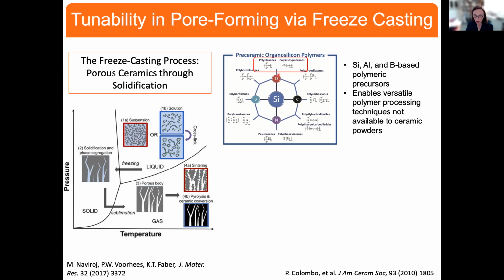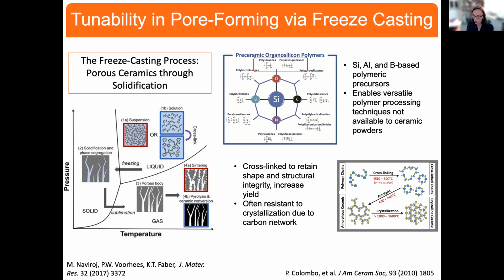So this scheme here enables a wide variety of techniques and materials. I mentioned that these are cross-linked. That step occurs over here in the solution step, and you can do that either using temperature or via a catalyst, as we often do. And then this can be pyrolyzed in the regime of 600 to 800 centigrade. And some of these materials crystallize as low as 1,000 degrees. Because of that carbon network, these materials are often resistant to crystallization, and many of the materials that I'll show you here are largely an amorphous silicon oxycarbide. Okay,